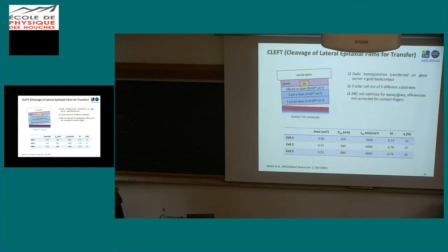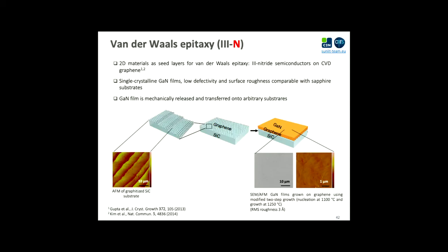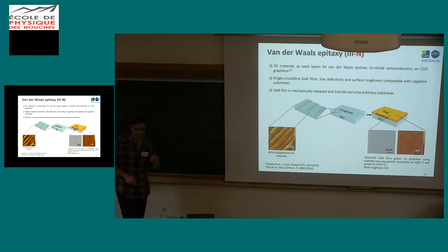So they demonstrate in this paper quite good efficiency. Those are without anti-reflection coating nor other optimization, using the same substrate three times. So I think it's an interesting technology. The other is very much more recent, two minutes and I'm done. It's basically coming from this van der Waals epitaxy. This van der Waals epitaxy is normally used for nitrides. The idea is you have your substrate, you put a graphene layer on top of it, and then you start to grow the gallium nitride.